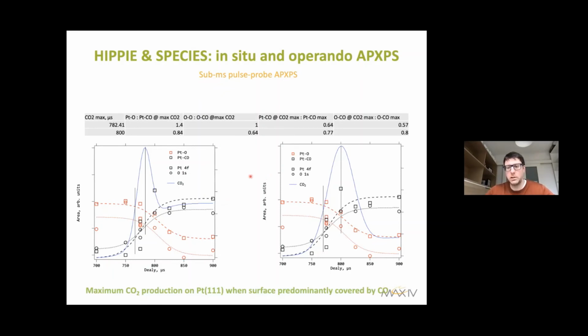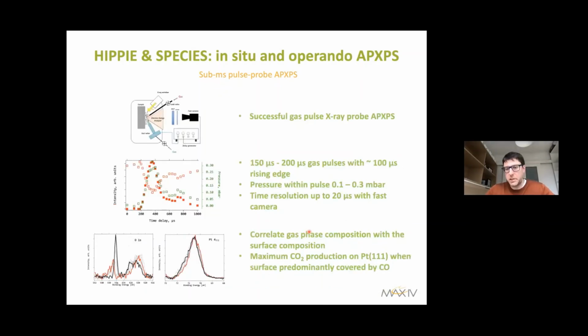And what does it tell us? Well, for example, the CO is being produced where the maximum CO coverage is, very close to the maximum coverage on platinum. It also tells us that CO2 starts being produced where very little CO is present on the surface. So with this we can say that we can reach time resolution of about 100 microseconds on the rising edge within this 0.1, 0.3 or half millibar gas pulse, and we can correlate the gas composition with the surface composition on the sample.